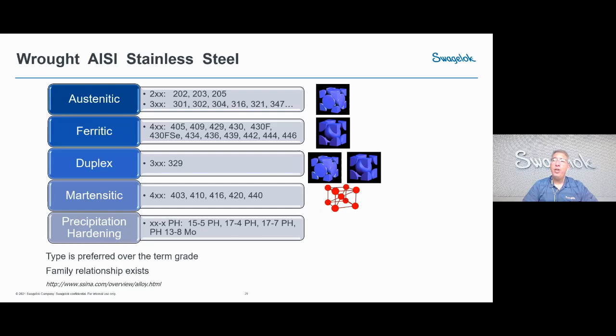And then as you work down, you can see ones such as ferritic. And the difference between those two is the crystal structure, which predominates according to the chemistry. So your austenitics are iron, chrome, nickel alloys. Your ferritics are iron, chrome alloys. Your duplex, which is a mixture of those top two, and that's controlled according to the chemistry. Those are also iron, chrome, nickel alloys, but not as much nickel to stabilize your austenite phase, enough nickel to have a mixture of those two phases.